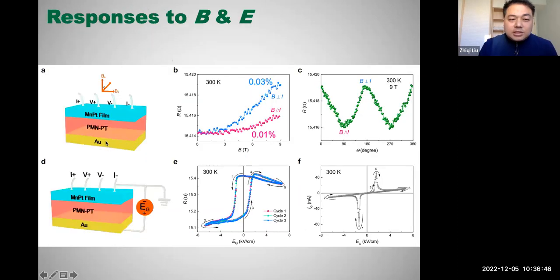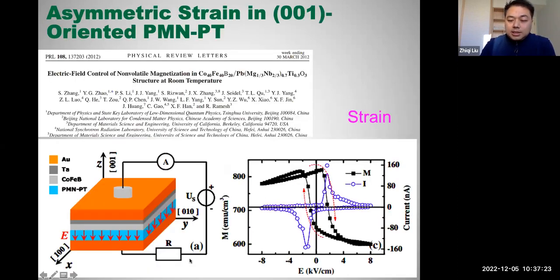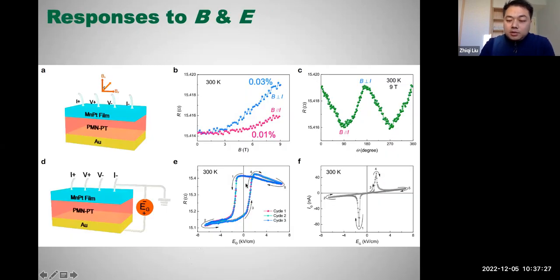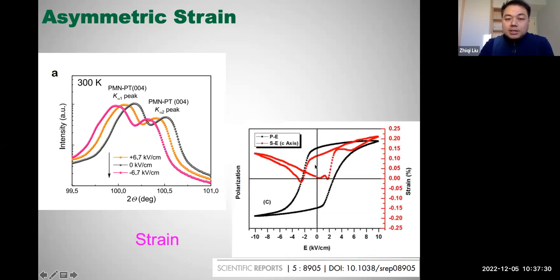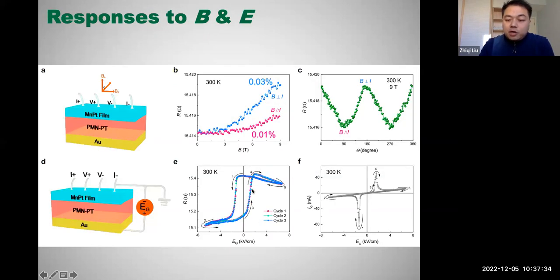We found the resistance of this antiferromagnetic film is quite robust over external magnetic fields. For example, if you apply an external magnetic field, you only get 0.01% magnetoresistance. It's very insensitive to external magnetic fields. But if you apply an electric field, you can get more than 2% resistance change. This is actually quite large compared with the magnetic field effect. It's 2 orders of magnitude higher. And if we look at our resistance curve, it's quite similar to the strain curve in the ferroelectric oxide. That means this effect is purely from the strain.